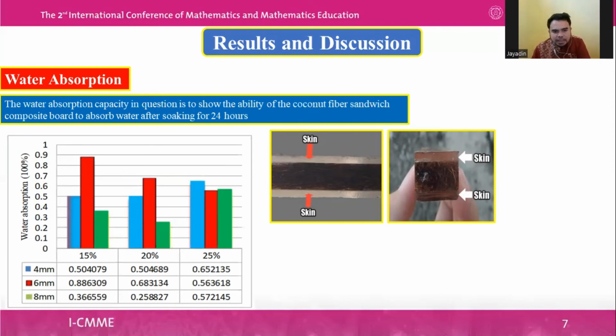This is because the 20% volume fraction specimen with a core thickness of 8 mm has only a few cavities or empty spaces on the left and right sides of the core that can accommodate water between the particles. The top and bottom of the specimen are glued with skin to close the pores of the composite board so that it can withstand the rate of water entering the composite.